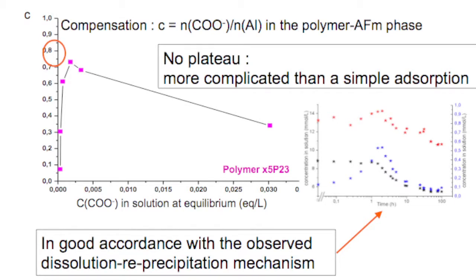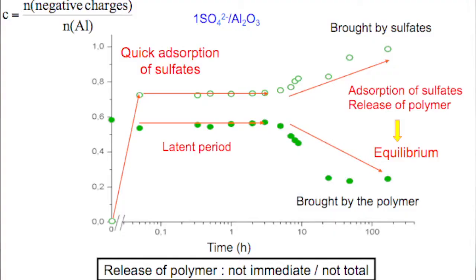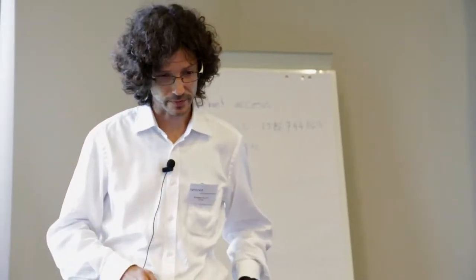Then a couple other nice things. You have here a plot of the amount of charges associated from the polymer to the solid or from sulfates, which are added at time 0 to the system. And what you observe is quick adsorption initially, a latent period, and then a decrease of the amount of polymer associated to the solid and an increase of the sulfate. So you don't suddenly go to monosulfate. No, there is a period in these experiments, under these conditions, with these concentrations, where you have to wait a certain time for something to happen.